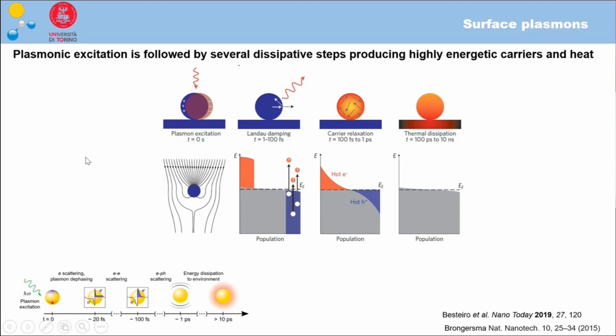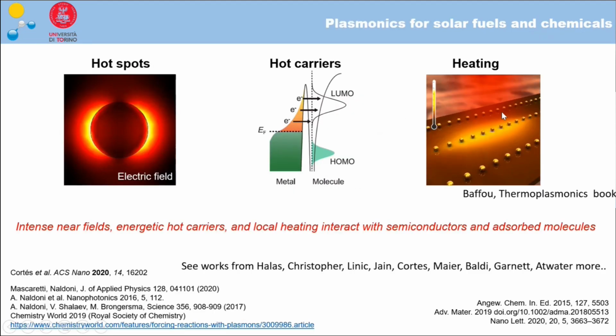For example, a very famous application is surface enhanced Raman spectroscopy, which uses the highly intense electric fields on the surface of rough plasmonic materials to enhance the signal of molecules that have to be detected. After this first moment, we have the dephasing or dissipation of the surface plasmon, which creates a non-thermal distribution of hot carriers, as you can see here. So we have highly energetic hot electrons and holes, which of course can be used for many different applications, and which survive for a lifetime on the order of picoseconds. Afterwards, there is a thermal dissipation, so we can use this material for creating intense local heating, and also in this case we can think of very common and famous applications like local heating for photothermal therapy.